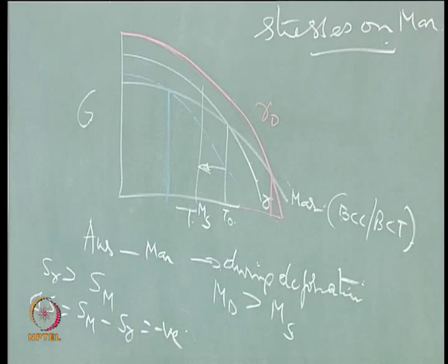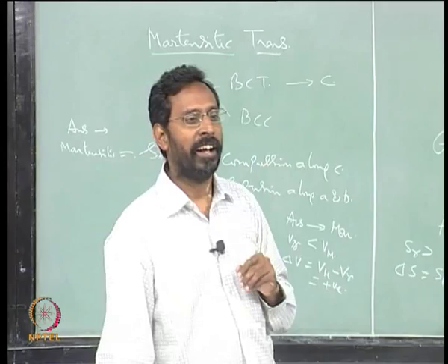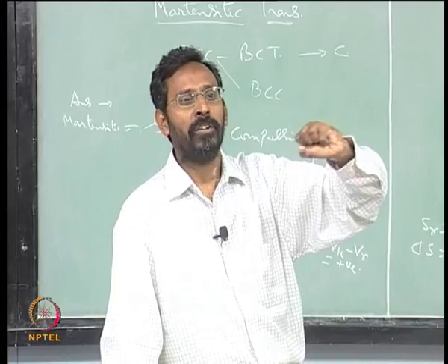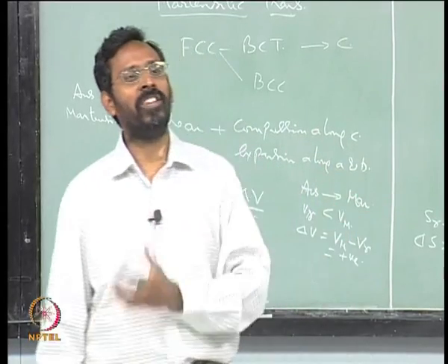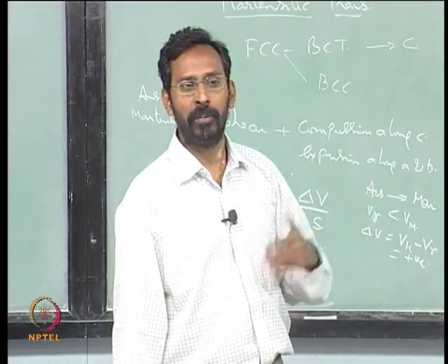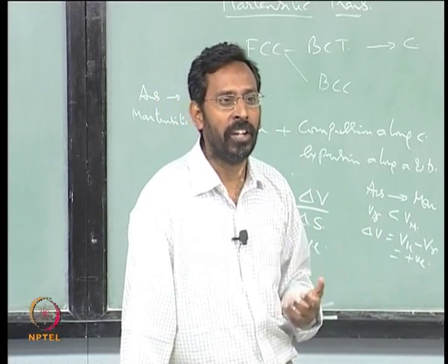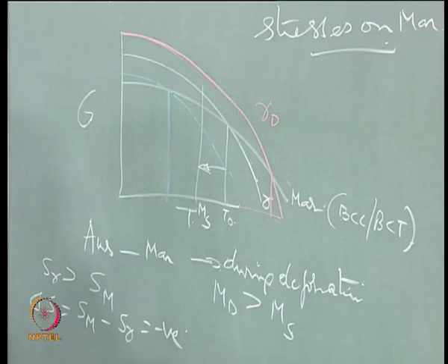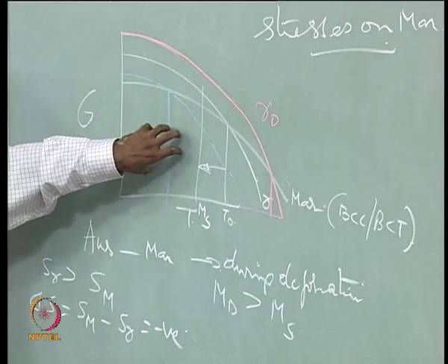So, in case you take iron or steel powders in the gamma state and then do a hipping and then you quench it and compare it with another steel which is produced by a normal route, you would see that the Martensite transformation occurs at a much lower temperature when compared to a normal steel. So, only in such a case can you actually confirm that, and for normal steels we do not need to use hipping at all. So, this is of more concern for powder metallurgy people.